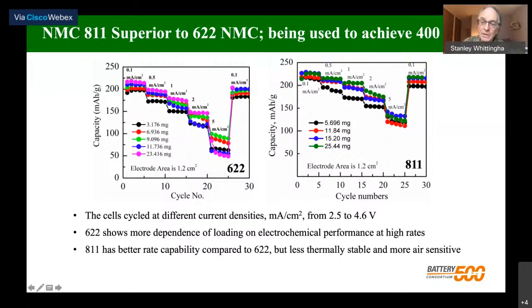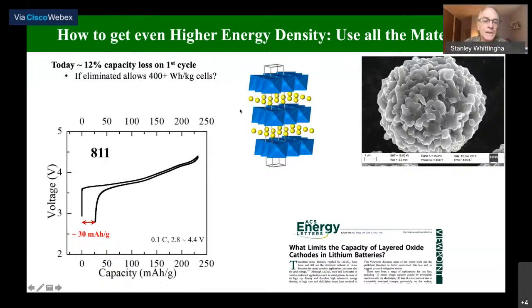program has switched over now to 811 from 622, but there are a few other ways we can improve the cycling behavior of this material. So if we look at these materials, this is again 811, here's the structure. This is what the actual powder looks like in commercial cells and the cells we investigated. The primary particles are about 200 nanometers. If you actually used those in the battery, they would not pack very well. It would be like using talcum powder or carbon black.